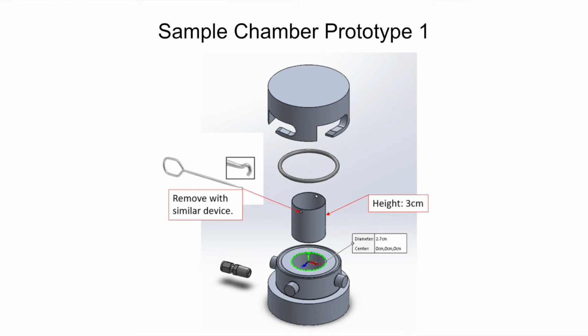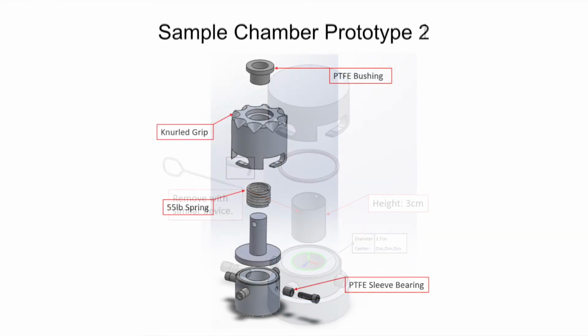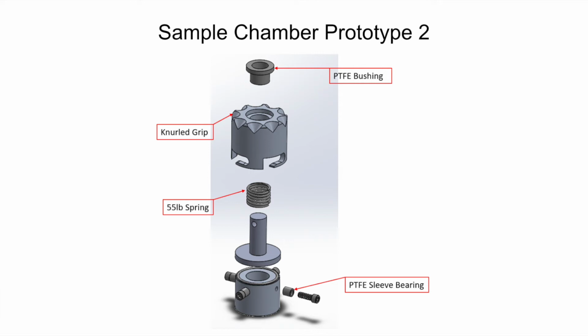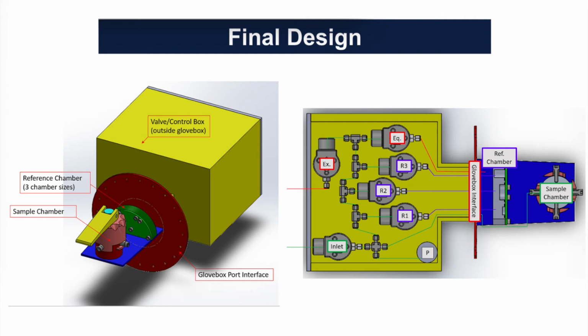The first design iteration utilized a quarter-turn camming latch closure that was very repeatable, but the shearing of the sealing face and the O-ring was deemed a possible point of failure. The second design iteration kept the camming latch closure, but added a sealing piston that was driven by a spring in order to compress the O-ring for a sufficient seal, and to have a repeatable mating face between the bottom of the piston and the top of the sample chamber. The camming latch pins were replaced with screws for improved manufacturability. Ergonomic grip was added to the lid for improved usability, and improved PTFE bushings were added to the points of shearing metal-to-metal contact. The final design was reached after extensive analysis and with care taken to meet the spatial and material requirements of Johnson Space Center.